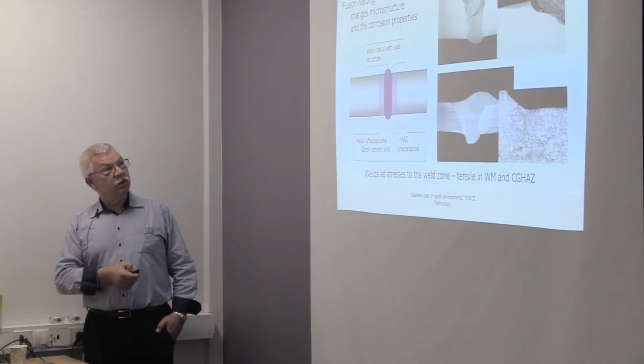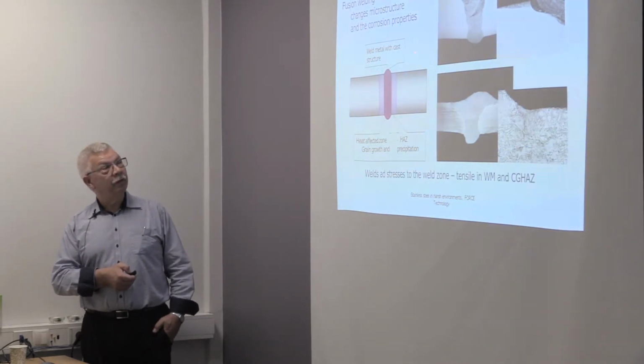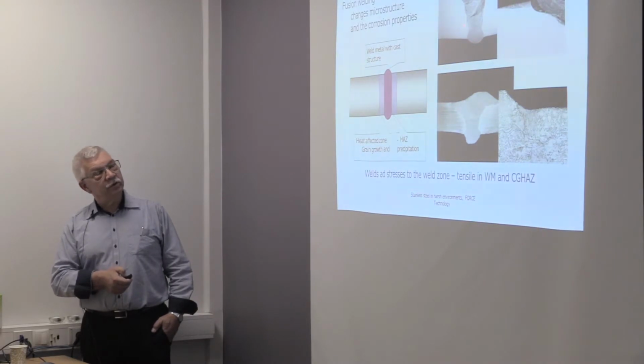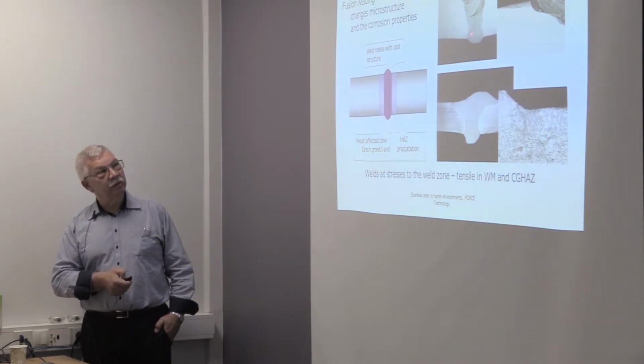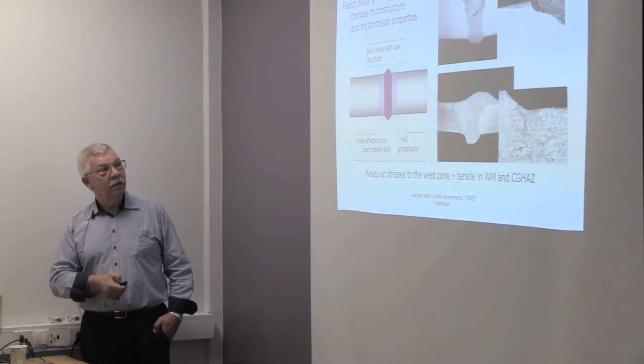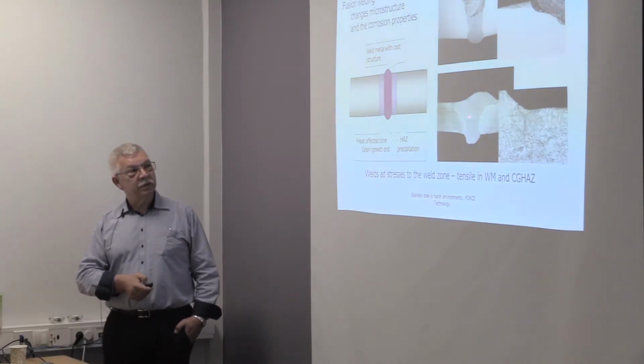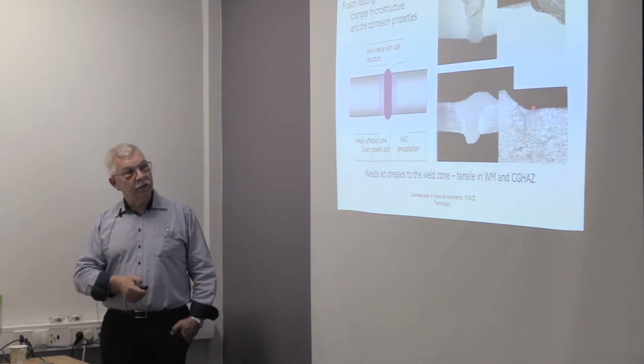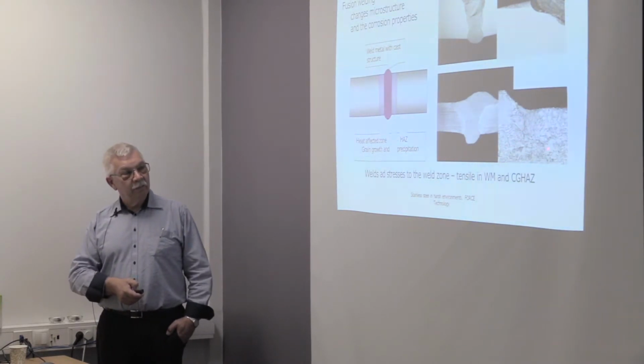In the heat affected zone, we will have grain growth. Not so much on the austenitic material. It's hardly visible that there's anything happening here. This is a longitudinal weld in the tube, so that's also weld metal. In other materials, it's different. This is a duplex stainless steel, and we have the heat affected zone here. We have the fusion line going like this, and as you can see, the material in the heat affected zone is very similar to the weld metal.